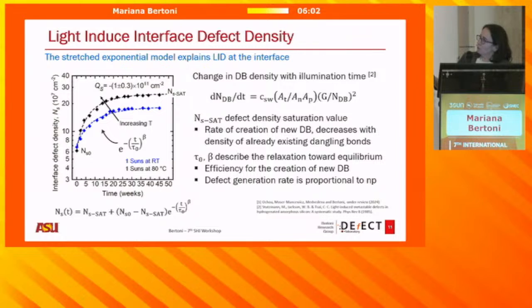And then you have your tau zero and your beta factor in your equation here, which describes basically the relaxation towards equilibrium. And that depends on the efficiency of the creation of dangling bonds and the different transformations that you have. And I'll mention some of the transformations in a second. The bottom line really is, and part of what Stutzmann was proposing back then was, that the defect generation really is proportional to your n_p factor.